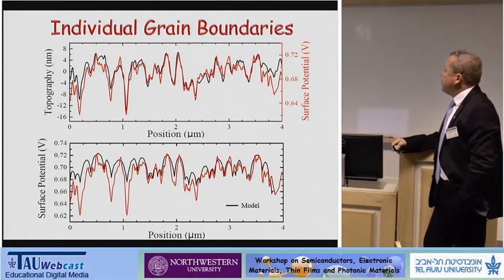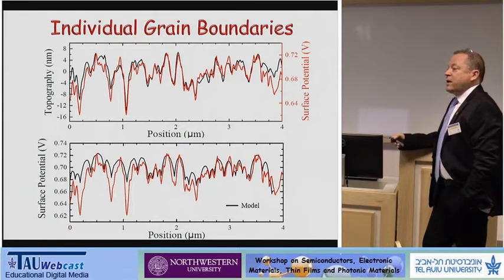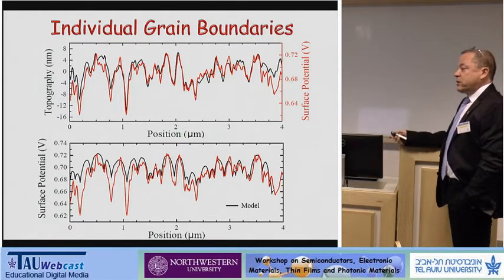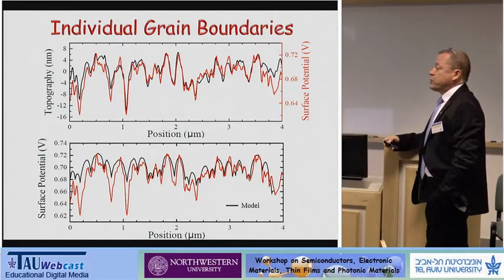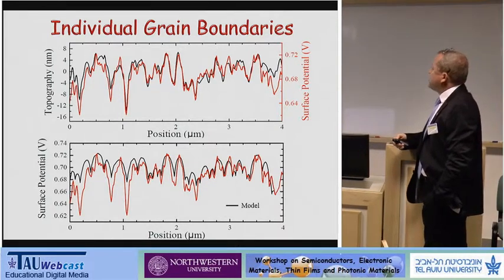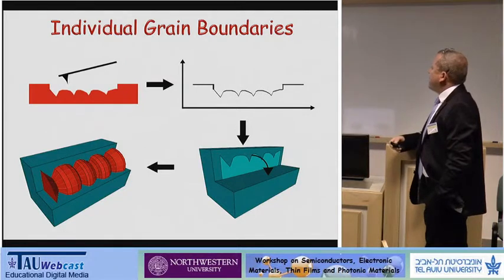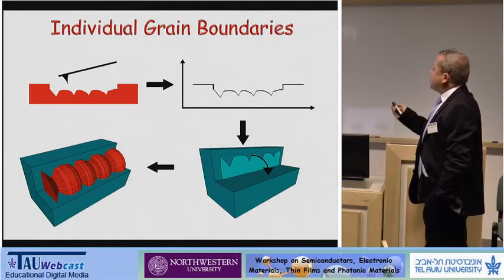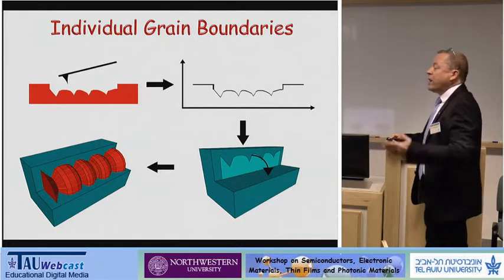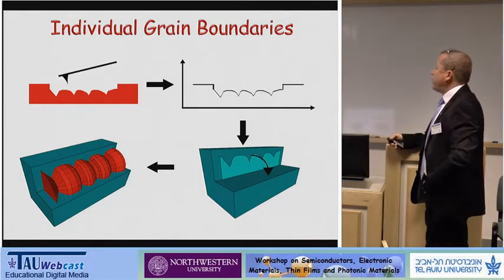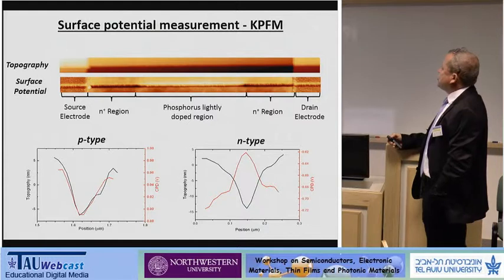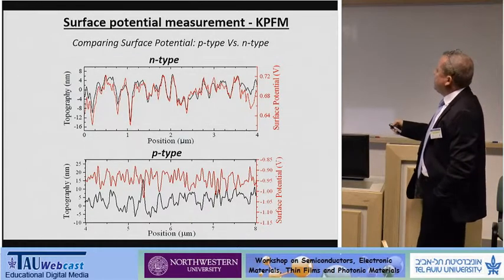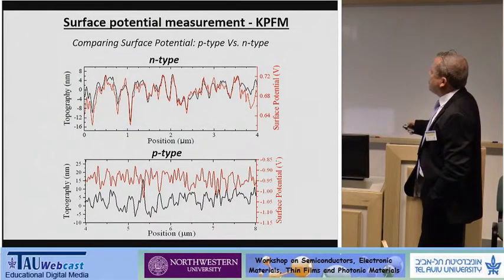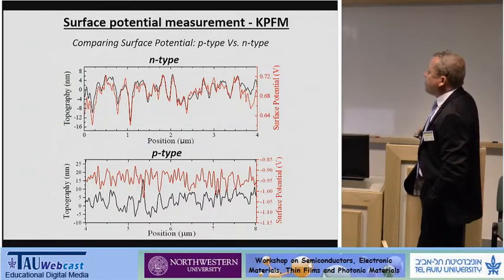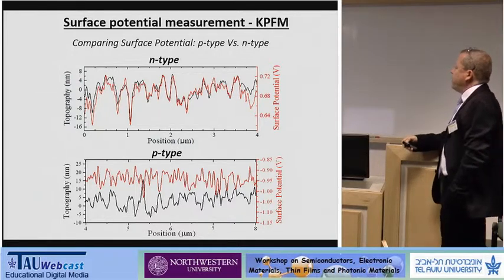And it turns out to be about 5 or 6 times 10 to the 12 occupied states per square centimeter at the grain boundaries, and this traps a lot of carriers. I will not elaborate on the simulation, but just to say that in the simulation, we included the exact topography of the grain boundaries. This was very important, just to prove to you that this is not an artifact. This is the result for an N-type polysilicon nanowire, and this is a result for a P-type nanowire. So you see that this is not an artifact of the topography.